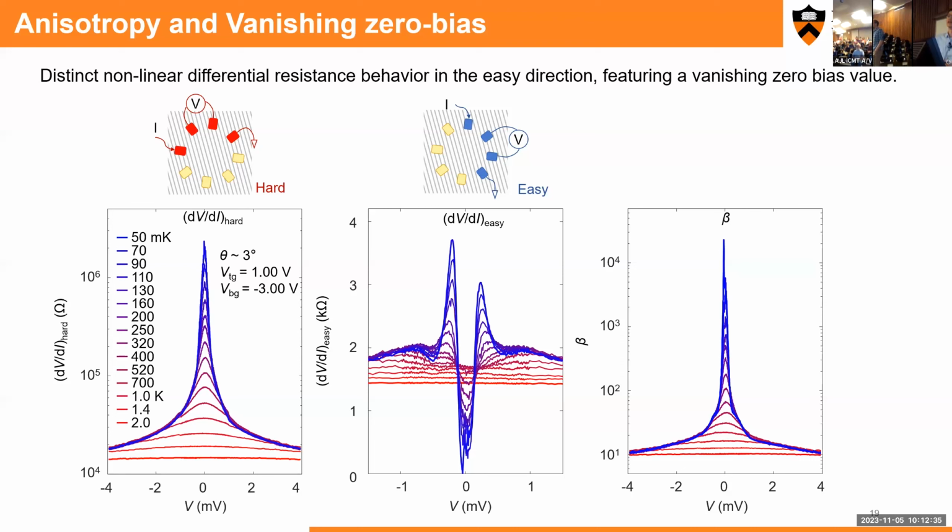And I actually have a comment, which is that, as you said, to get the sliding Luttinger liquid requires very fine tuning and a lot of optimism. It's much easier to get a sliding phase if you have some of the modes on the wire gapped. We looked at a sliding Luther-Emery liquid, but these are multi-component systems. If some of the degrees of freedom are gapped, it's much easier to get a sliding phase.